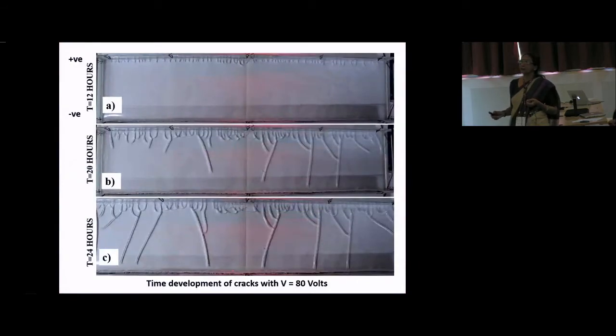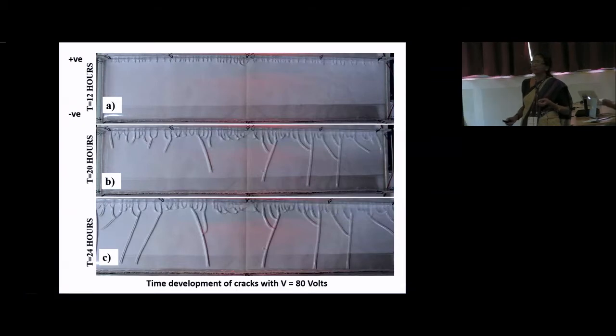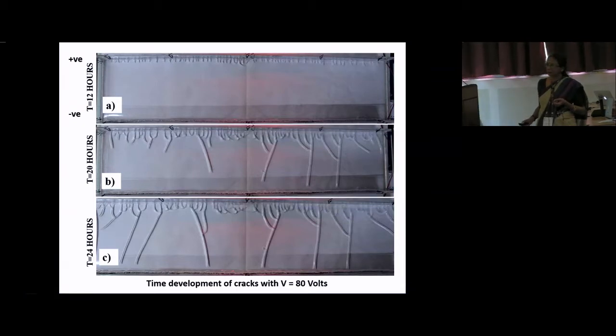After 12 hours of drying, you can see that from the positive electrode, the cracks have started to appear. And after 20 hours, these cracks are proceeding, but what is interesting is that they are not proceeding straight. The neighbors are merging together, and so as we go on, the number of cracks is gradually decreasing. Here, they have almost reached the other end, and this is after 24 hours, and you can